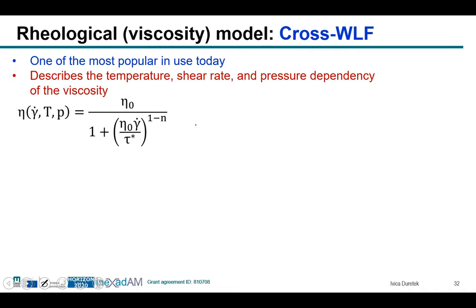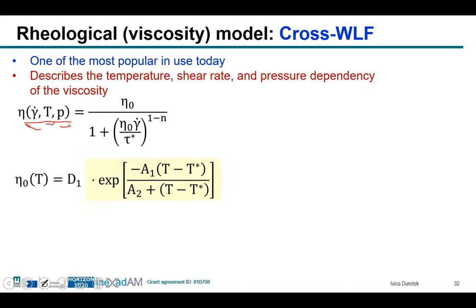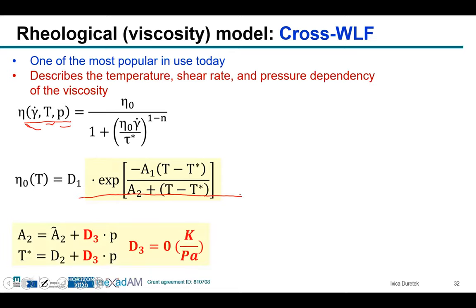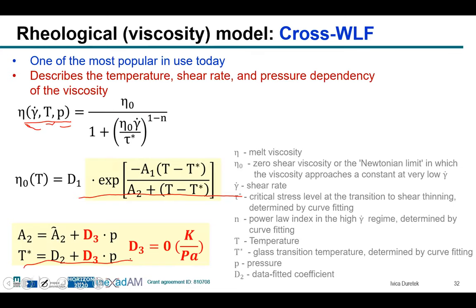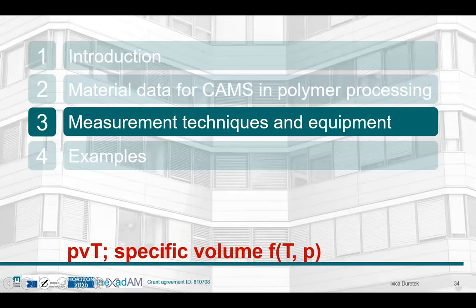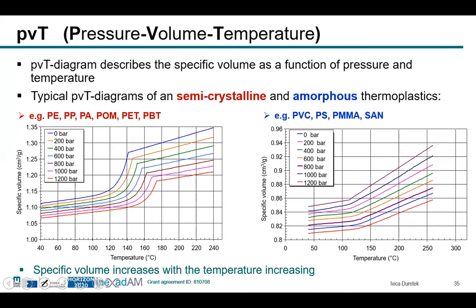For the mathematical approximation of the measured viscosity data, a lot of models exist. One of the most popular models is the so-called Cross-WLF model. With this model, it is possible to describe the viscosity dependence on shear rate, temperature, and pressure. This term actually describes the temperature dependence, and the pressure dependence is described with A2 and D3. So for the measurement of the viscosity, we have at the Institute several different devices.